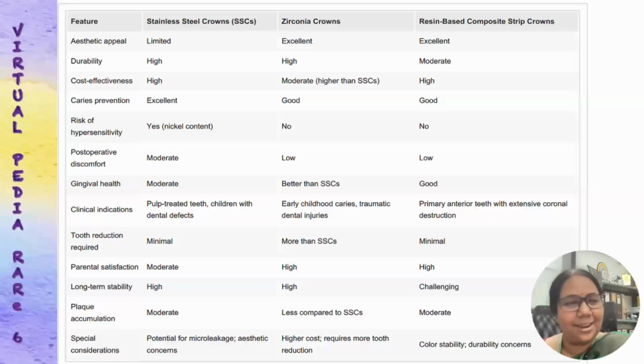Clinical indications: all these three are basically indicated for teeth where there are serious defects, in pulpectomy treated teeth. But of course, we can use a stainless steel crown in a tooth with bruxism, which we may not be able to with the others. We already looked at certain situations where we cannot use strip crowns or zirconia crowns. The tooth reduction is one major disadvantage of the zirconia crown. We said that 1.75 to 2 millimeters of overall reduction is required for zirconia crowns, which is much more than what is required for stainless steel crowns. Parental satisfaction is the highest with zirconia crowns and also strip crowns, whereas there is moderate reported parental satisfaction with the stainless steel crowns.